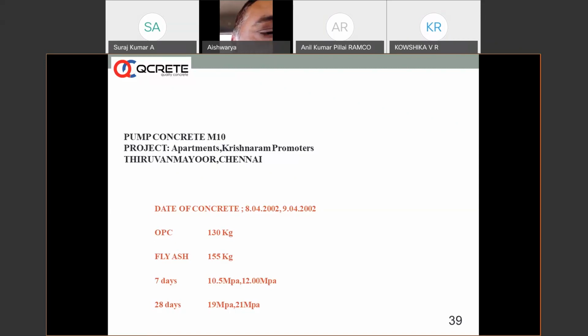So 130 kg of OPC was mixed with about 155 kg of fly ash, and you had about 10.5 MPa to 12 MPa in 7 days. Of course, we had better strength, and the requirement was only 10 MPa. Here, the strength was not the point actually. The point is that pumpability was significantly increased using fly ash.